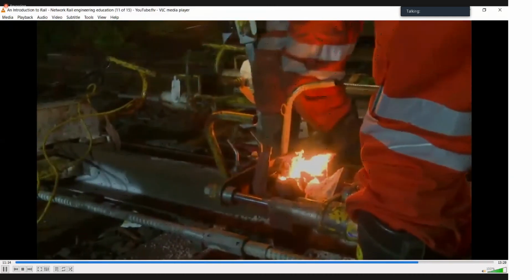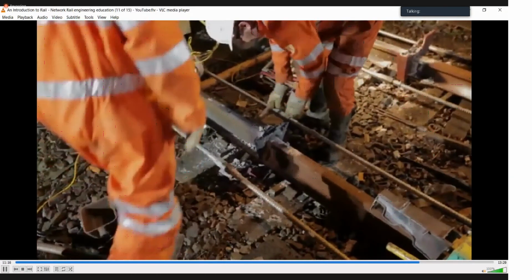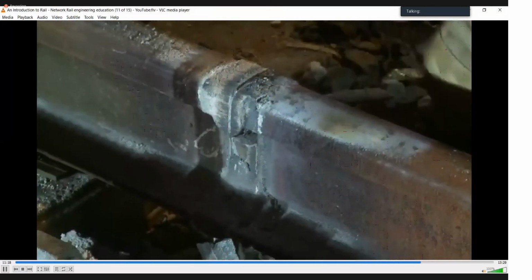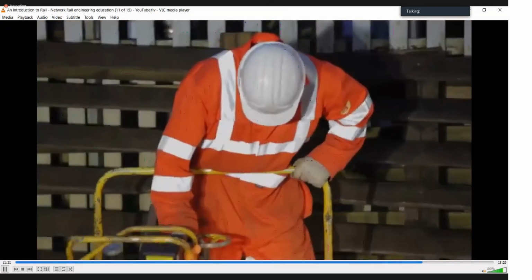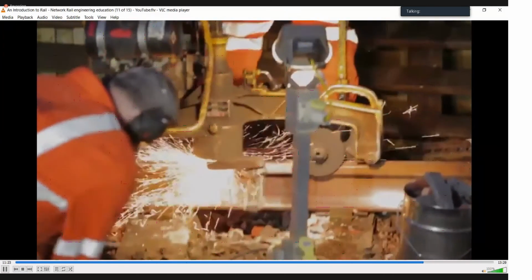The mould and excess weld metal is removed while it is still hot. The stripped weld is then profiled to exactly match the rail profile and produce a smooth finish.